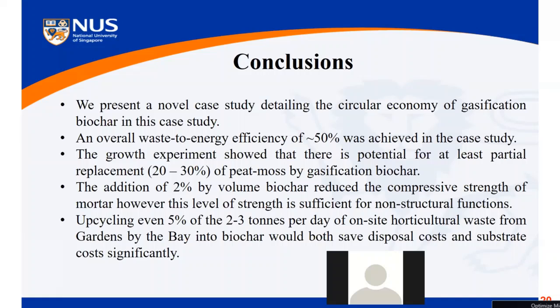Furthermore, the addition of 2% by volume of biochar reduced the compressive strength of the mortar. However, this level of strength is sufficient for non-structural functions. We also found that by upcycling about 5% of the 2 to 3 tons per day of on-site horticultural waste from the test bedding site into biochar, we could save disposal cost and substrate cost significantly.